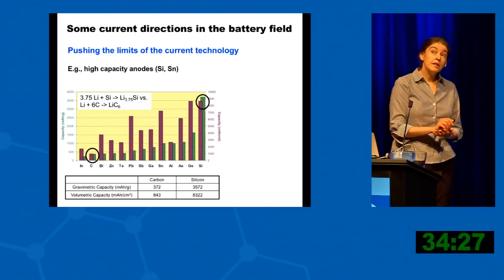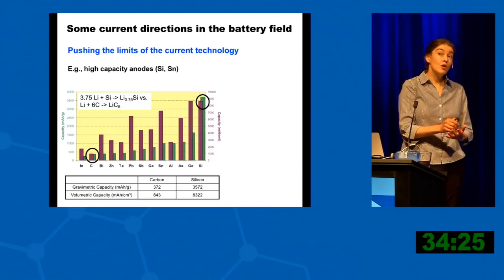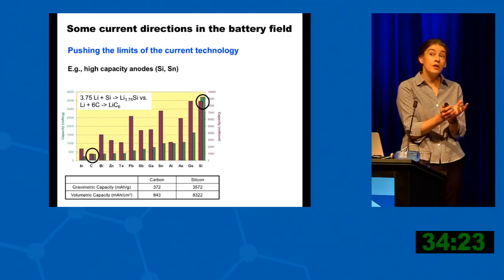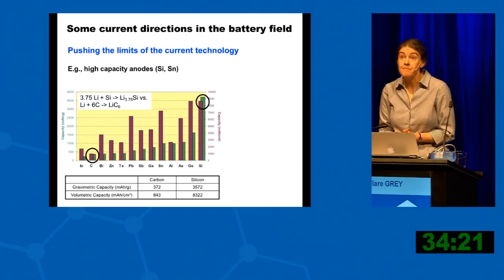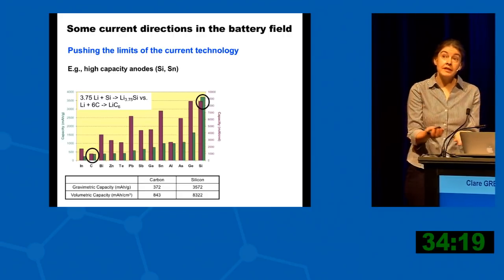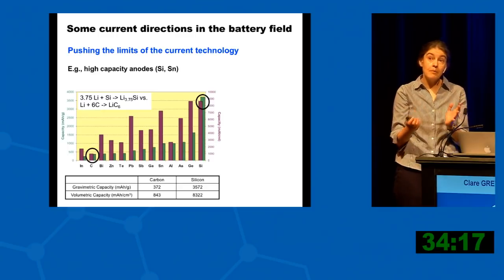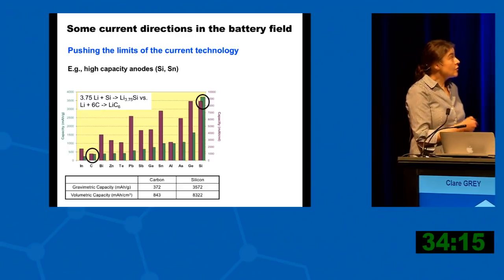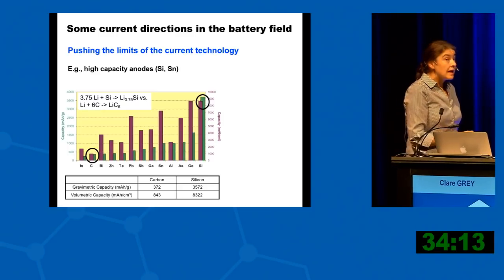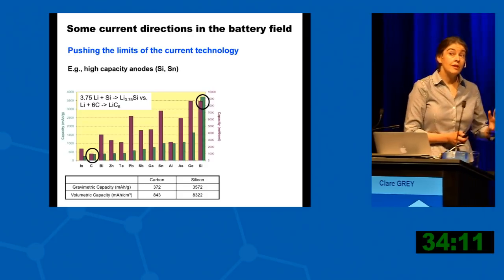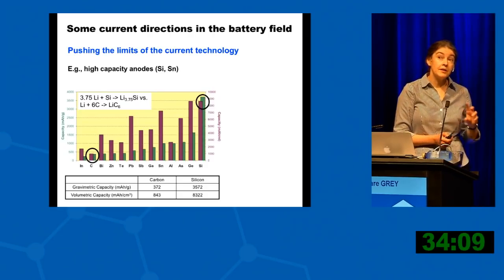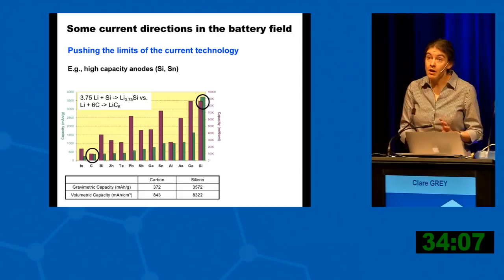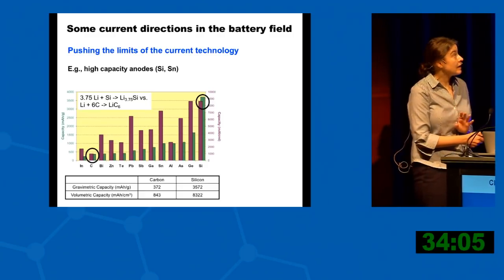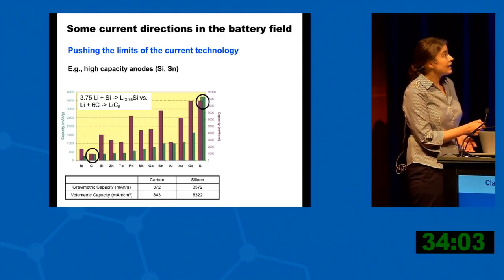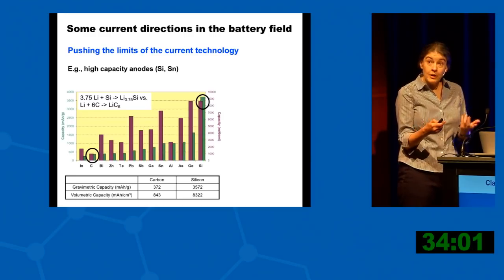The challenge with silicon is that it comes with a massive volume expansion, essentially associated with the size of lithium metal. It doesn't form a stable passivating layer, and I'll come back to that later, so you get continued reactions. At the moment, the strategy on the industrial side is to combine silicon with some carbon to get a little bit of increase in capacity, but not put all of your eggs into the silicon basket, which still has longevity issues.